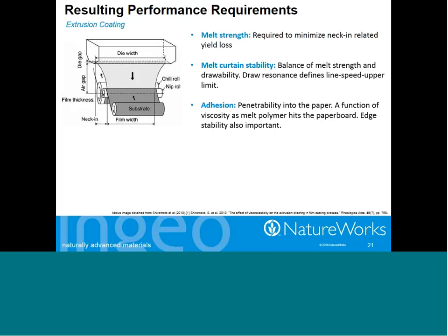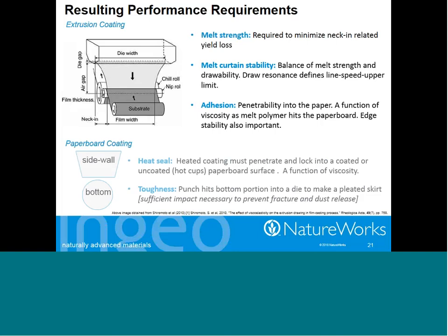And then the third thing I've mentioned here is adhesion. So the polymer has to adhere to the paper with sufficient strength, because it's actually the glue that ends up holding the cup together, as well as providing the protection for the paper from the liquid that's inside. The other part of it is, I mentioned the heat seal. It's the glue. Part of it is toughness as well. So we've got a sidewall and a bottom, and this bottom is going to get punched and a pleated skirt put in it, and the polymer needs to stay attached to the paper stock all during that process. If it flakes off, we're going to get poor formation of the cup and poor integrity of the cup.